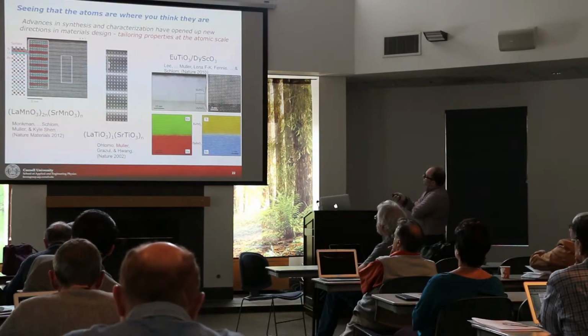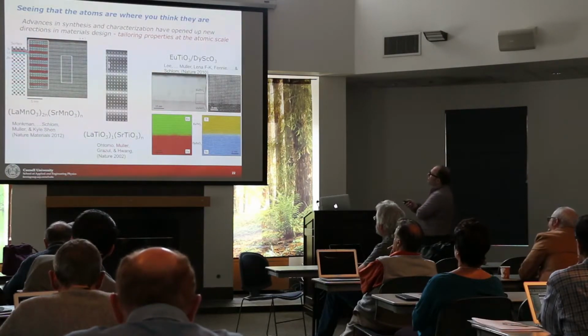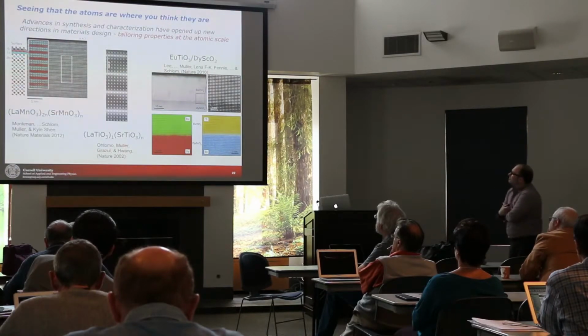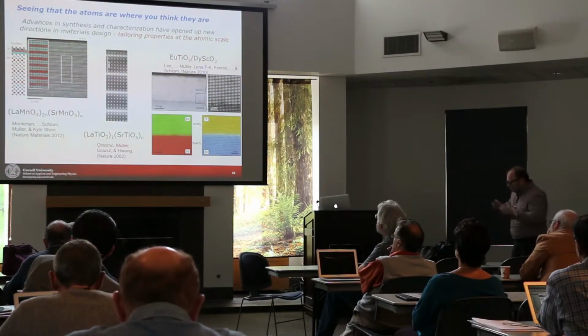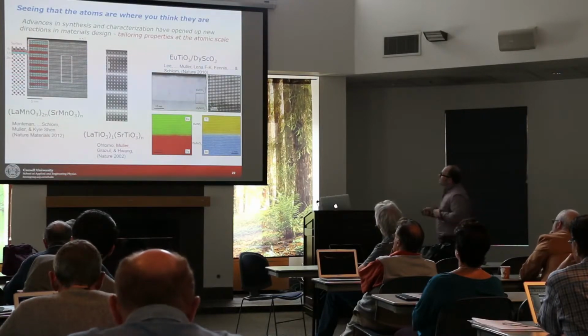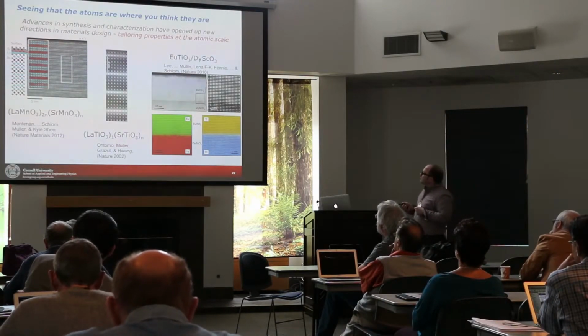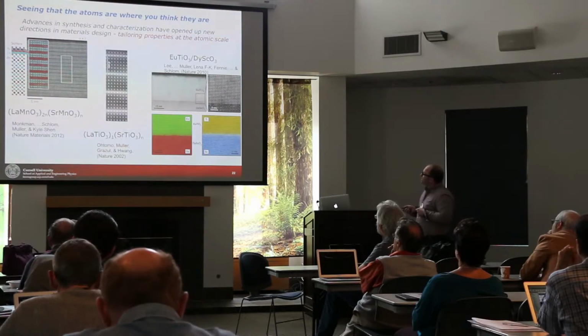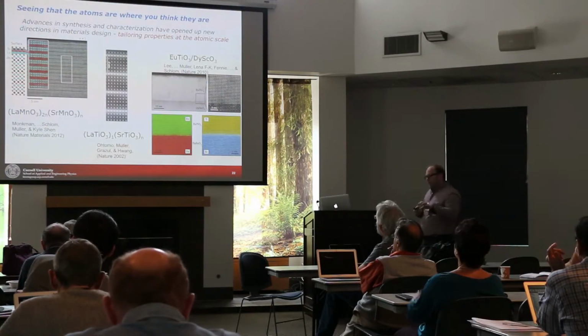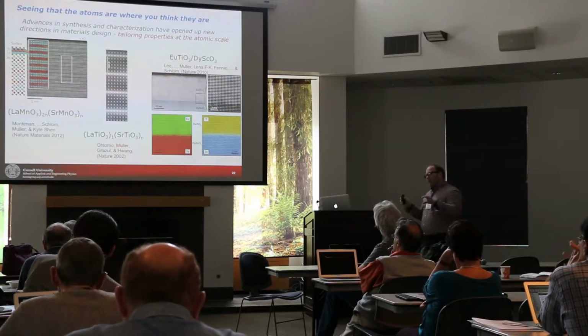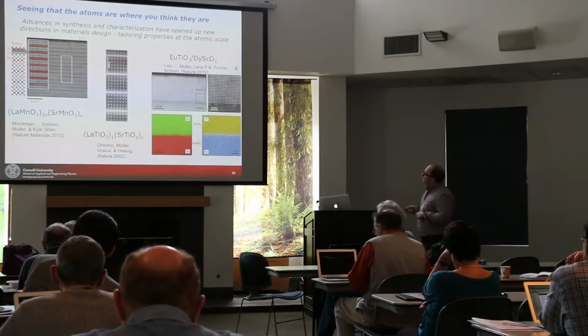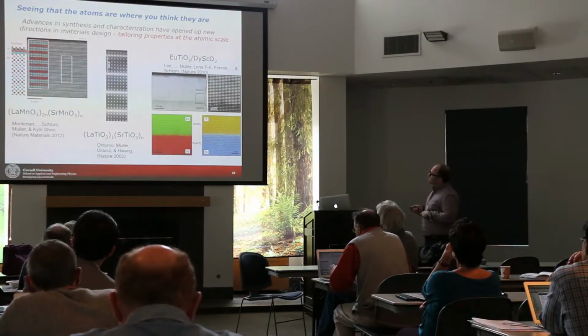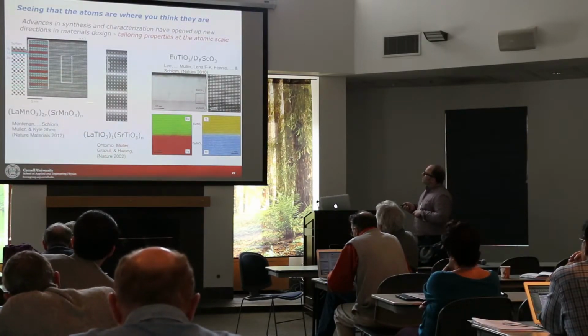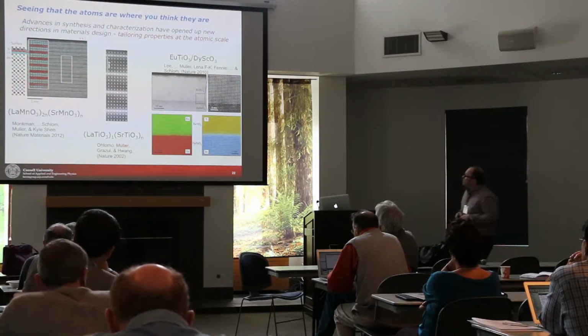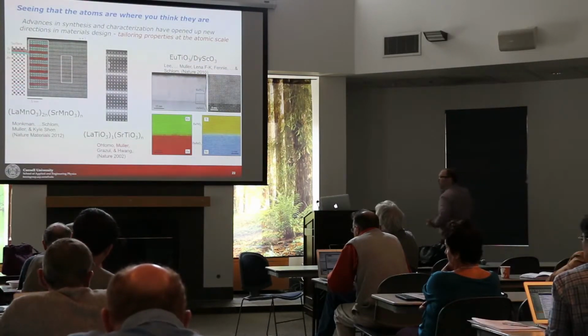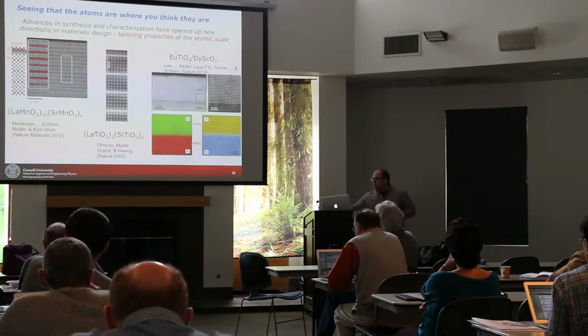This one here, the center one, perhaps 10 years ago or so, really ignited this field of complex oxide interface physics, because this is an example of taking two materials, lanthanum titanate and strontium titanate, which are both insulators. By making this digital superlattice, an active interface between these two insulators, a non-insulator, a two-dimensional electron gas, emerged. This is a great example of what one can do using these techniques.